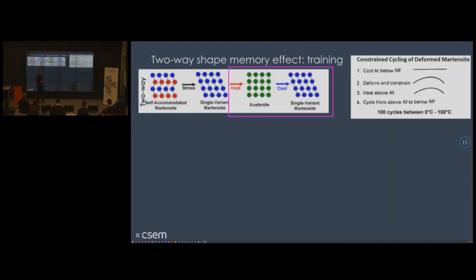There are several ways how to train nitinol or shape memory alloys. In this case, we used so-called constraint cycling of deformed martensite. So in this case, you set the shape, so you have at the beginning the default shape that is upon laser powder bed fusion. Then you deform it at cold state into a different shape, and you heat above AF and below martensite finish. We did this 100 times on a simple